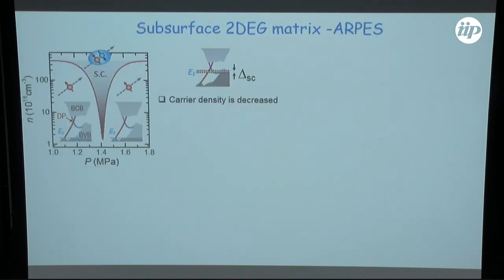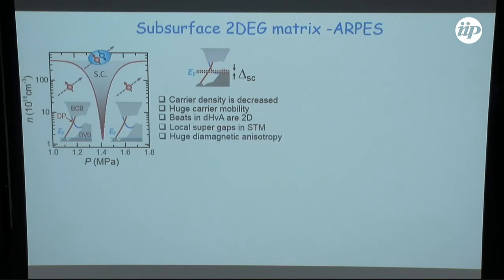So what I argued before was that now you see we have a system where the carrier density actually drops down by over 2 orders of magnitude in the regime of superconductivity, and that there's huge carrier mobility. I'm not showing you this. We also see the beats in the de Haas-van Alphen, which are 2D, which are typical of semiconductor beats in a 2D electron gas. We see huge diamagnetic anisotropy and local super gaps.